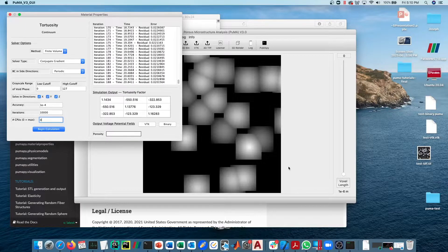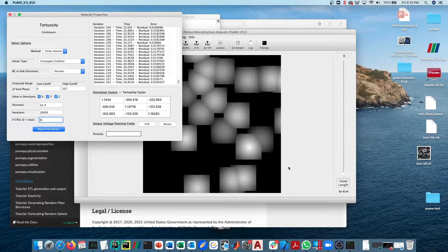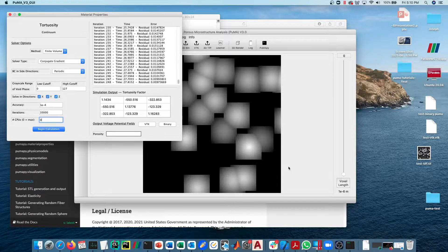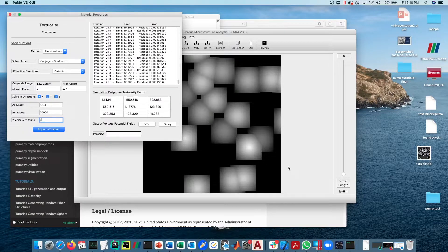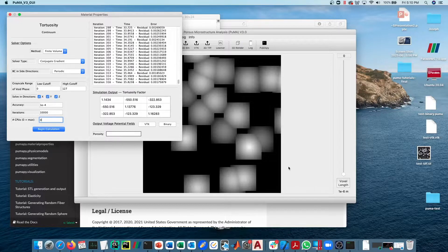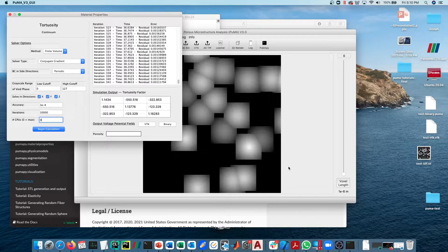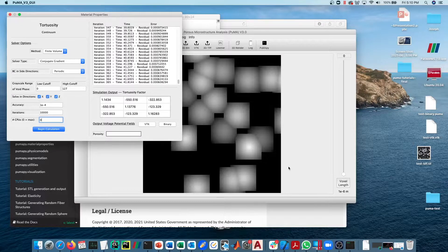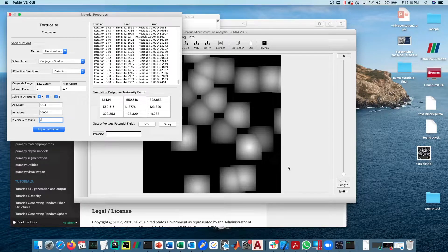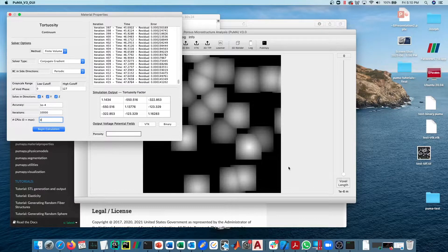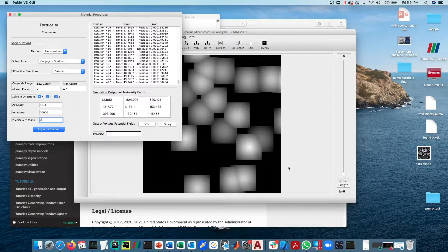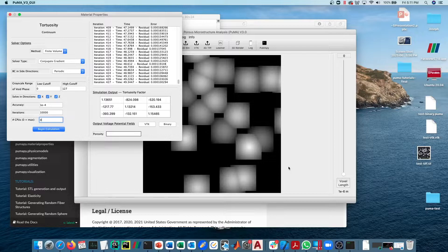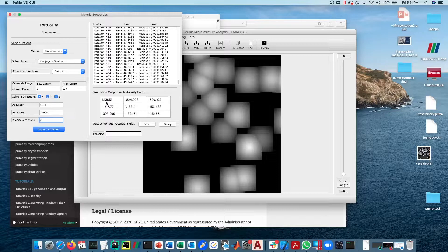While this is running, I'll make a quick note about representative elementary volumes. Since we're running here on a very small domain, something like 128 cubed, this is definitely not a representative volume. By representative volume, I mean that if you were to generate the same material again with a different random seed, or if you were using tomography and were to run it again with a different tomography image, you would end up with the exact same value within plus or minus a percent or something like that—whatever your threshold is, which is a little bit arbitrary. We define that as a representative volume.